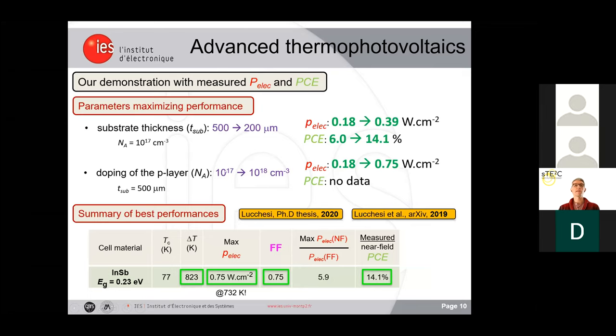At the bottom of this slide, there is a summary of the best performances that we got. So a record temperature difference of 823 Kelvin, a maximum electrical power density of 0.75 watt per square centimeter at the emitter temperature of only 732 Kelvin, a fill factor for the PV cell reaching 0.75, and a measured near field power conversion efficiency reaching 14%.